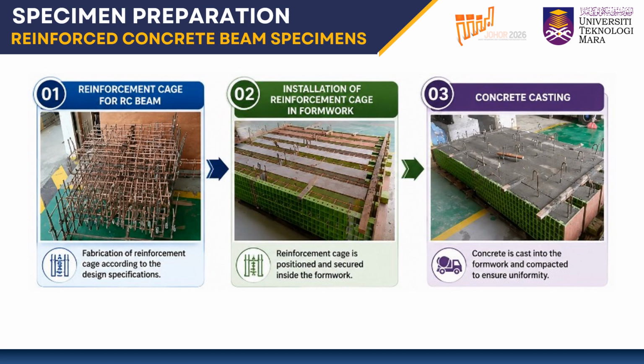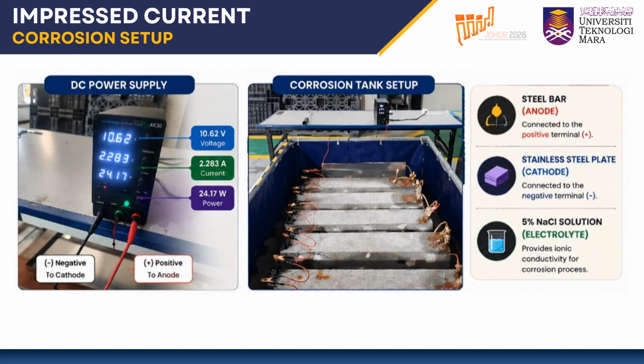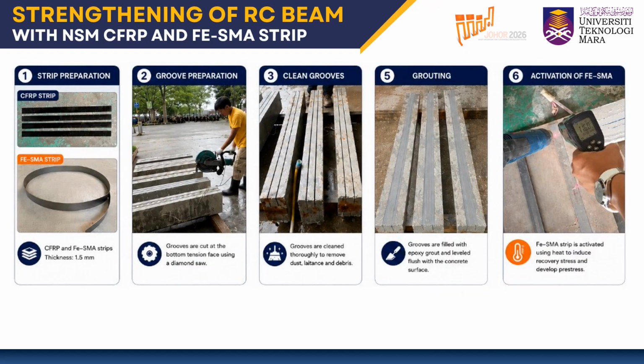RC beam specimens were prepared by assembling the reinforcement cage, installing it inside the mold, and casting concrete according to the design specification. Accelerated corrosion was produced using the impressed current technique. The reinforcing steel acts as the anode, a stainless steel plate serves as the cathode, while a 5% sodium chloride solution simulated a marine environment.